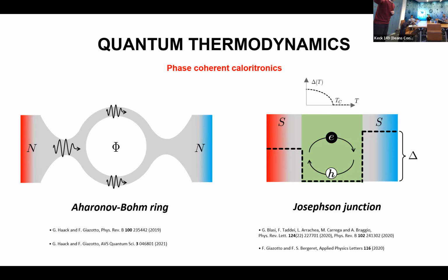And for example, we used this Andreev reflection in a collection of works that I did during my PhD. And we showed that using such Andreev reflection, you can indeed create an Andreev interferometric mechanism inside your junction. And almost in the same fashion as it happens for the Aharonov-Bohm ring, by using this interference, you can create thermoelectricity.